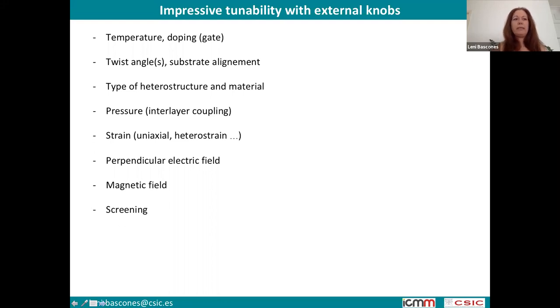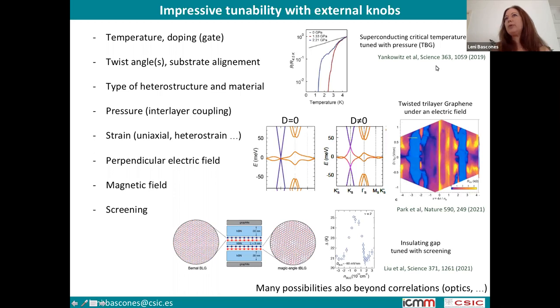Again, here there are some examples. For example, people have been able to tune the superconducting critical temperature with pressure. You can see here how it has changed with the pressure. This is an example of a perpendicular electric field. This is without a field, the bands in the twisted trilayer graphene, and this is with a field. You can see that there is a difference here in the bands. And here, this is doping, this is electric field, this is a resistivity plot. You can see that there are important differences as a function of the electric field. So it's an external knob.